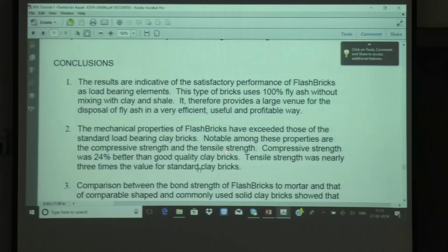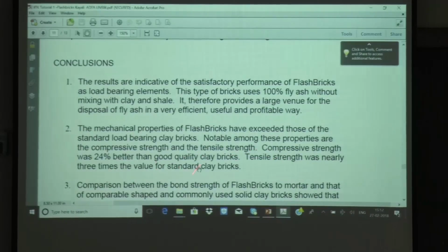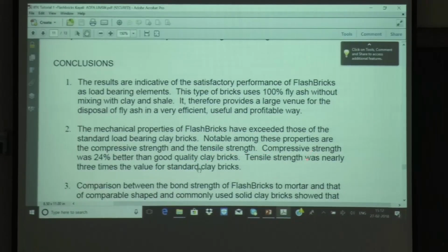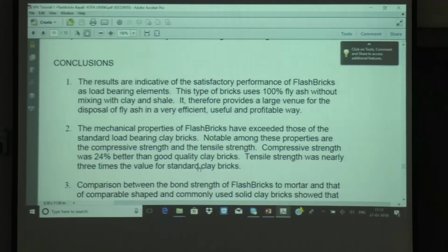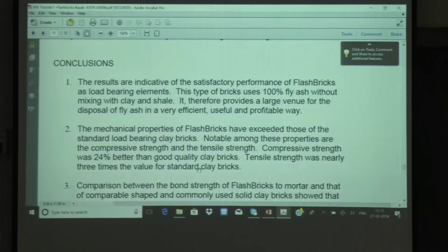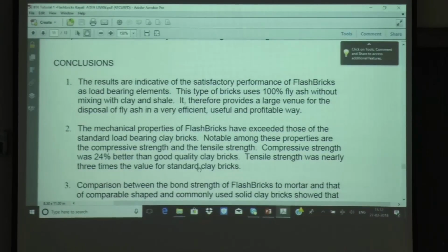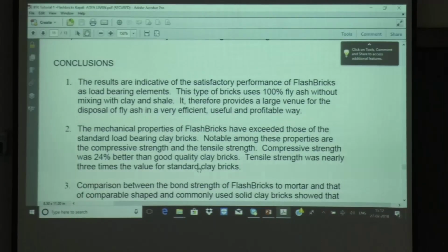In flash bricks, compressive strength was 25% better than the clay bricks, and tensile strength was nearly 3 times the value for the standard clay bricks. That's a fantastic thing, because normally clay bricks have much lower tensile strength, okay? And the reason why the tensile strength is about 3 times more, remember I have been mentioning all this time,